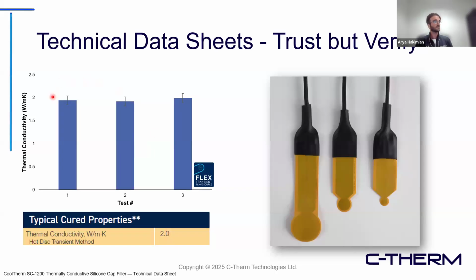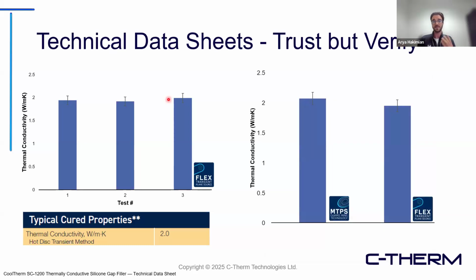So spec at 2, and of course, when we talk about technical data sheets, trust but verify. So we measured these well within the expected range. So definitely a good quality material here. But I thought it'd be interesting to similarly test it with the MTPS. A question we get a lot is how do these different methods compare to each other? And as I was saying, with some methods, there are certain levels of bias that can be introduced. So how does that come up and to what extent, right? So in this sample here, I would say between the 2 results, they're both within that 2 watt per meter Kelvin range, within 5 to 10%. So really good agreement here between the 2 different methods.